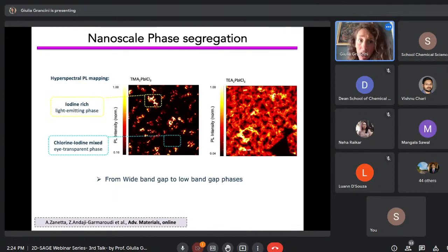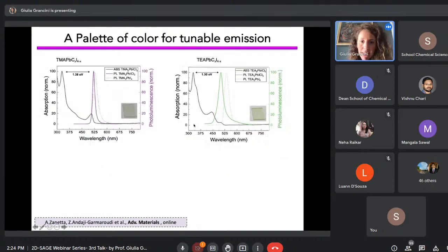As a result, we do have a material with a lot of phase segregation, with iodine-rich regions and chloride-rich regions. Why is this interesting? This material is interesting because it absorbs mainly in the UV region. So basically this film, which is rich with chloride, is transparent to the human eye. However, it emits in the green. So you can create a palette of color for tunable emission.